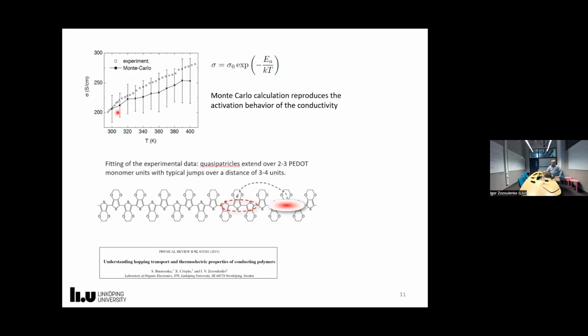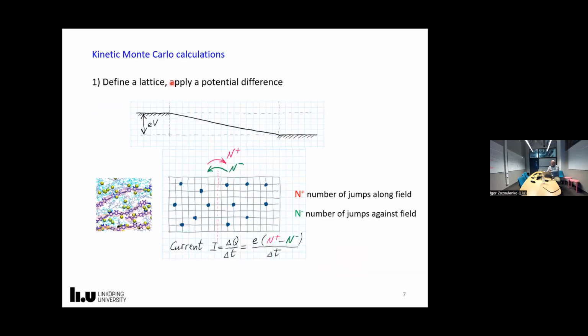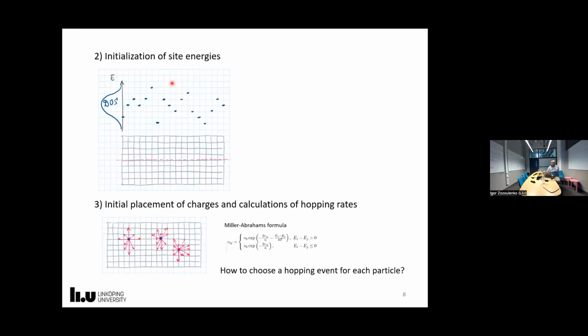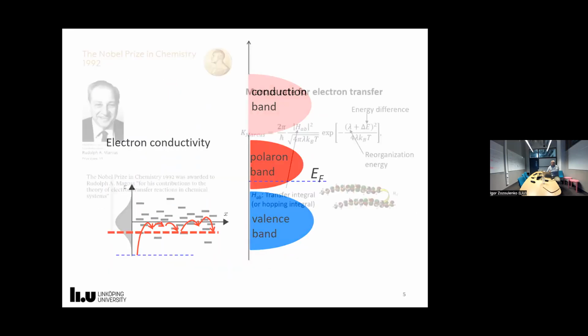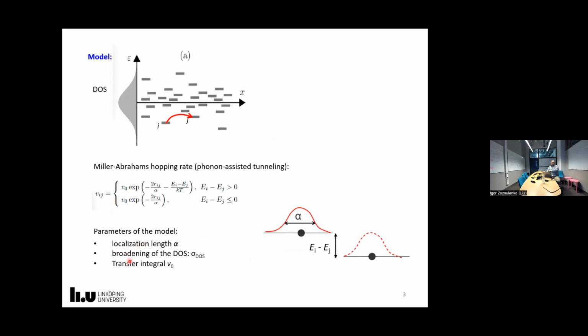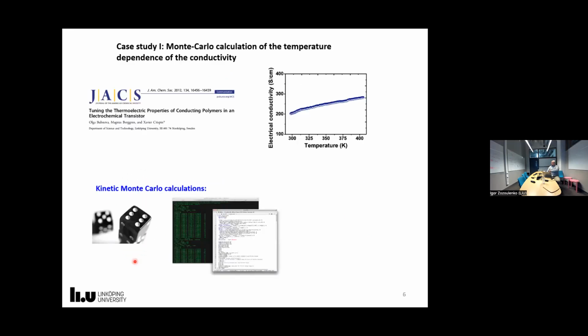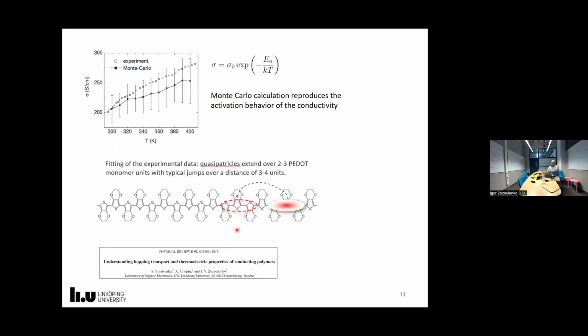We see that we reproduce this temperature increase, the activated behavior. But what is more important, we can fit our parameters. As I mentioned, there are some parameters in the Monte-Carlo technique that you are supposed to fit: the localization length, broadening of the DOS, transfer integrals. From the fitting, we can extract these parameters, and this plot is a graphical illustration of them. According to our calculations, these quasi-particles are delocalized over 2-3 monomer units, and a typical jump distance would be 3-4 units. So using these Monte-Carlo calculations, we can extract, I believe, important information about the nature of electron motion in conducting polymers.